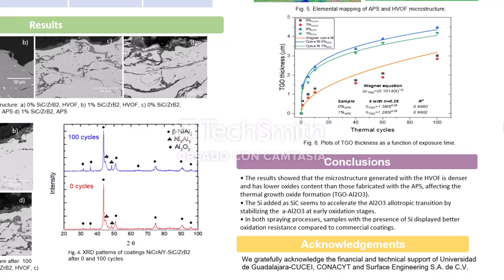The addition of silicon carbide seems to accelerate the aluminum oxide transformation by stabilizing the alpha aluminum oxide at early oxidation stages. In both processes, coatings with the presence of silicon display better oxidation resistance compared to commercial coatings.